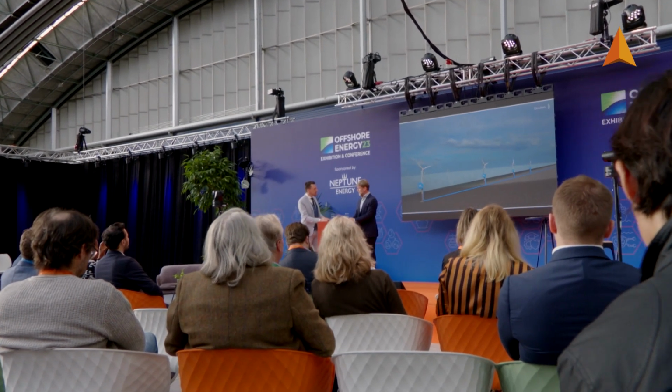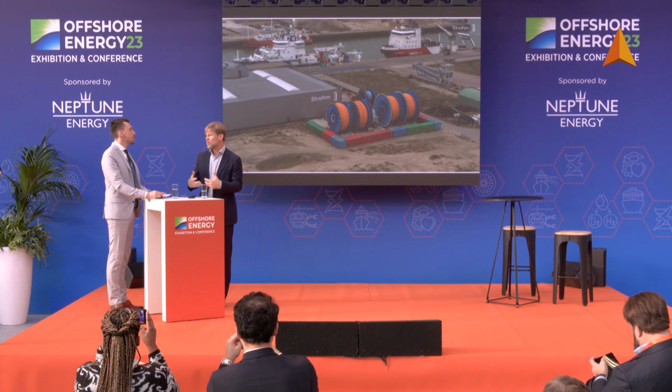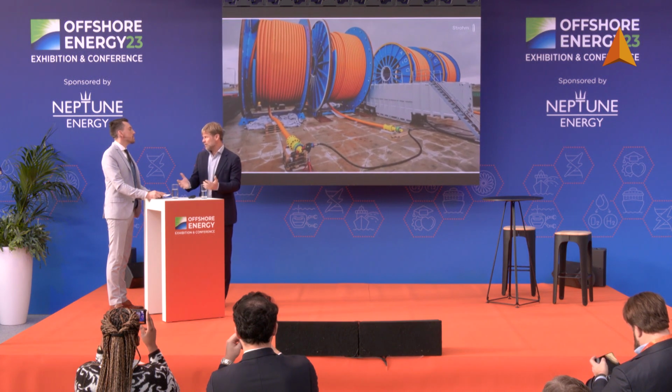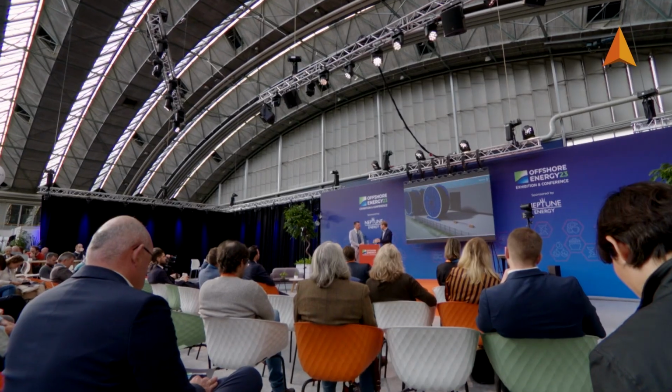It's both actually, because hydrogen in the tube can cause hydrogen embrittlement if you have steel as your main material, and that's amplified if you have fatigue stresses in a dynamic environment, which the sea is very dynamic. Then steel pipes are not the best solution, because hydrogen embrittlement will ultimately destroy your pipe. So you need a material that does not degrade under hydrogen as a fluid inside. And that's what a composite material does.